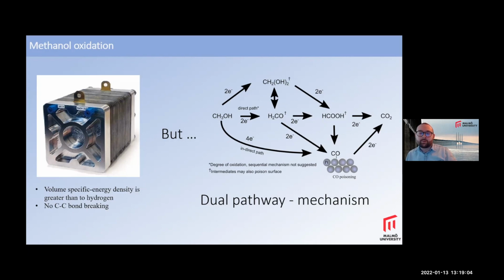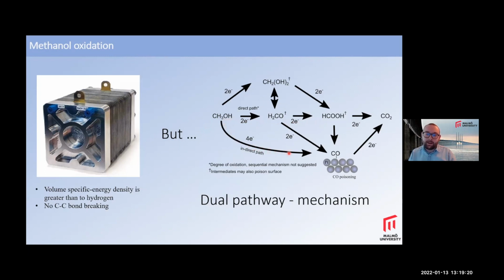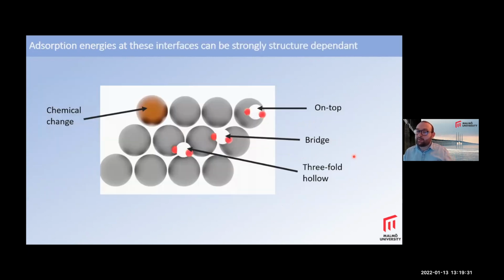But the main problem associated with this is the so-called dual pathway mechanism, where instead of going the direct oxidation path, there's an indirect path, especially on platinum surfaces, where you produce CO, and this poisons the surface and reduces the efficiency of catalysts. Adsorption energies at these interfaces can be strongly structure dependent, so it can really matter what the interface looks like and what the available sites are for how the reaction proceeds.